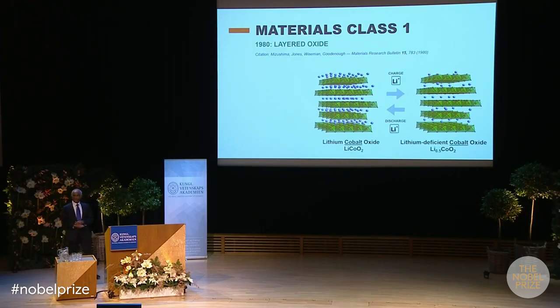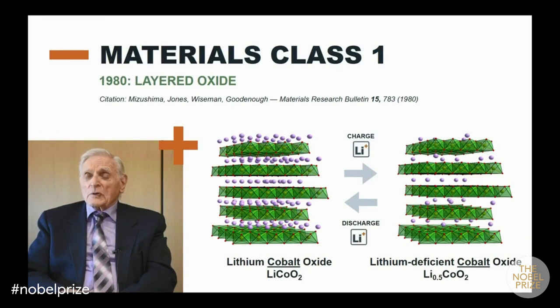The first family of cathodes Professor Goodenough's group developed was a layered oxide. I started with lithium cobalt oxide because it was a layered compound with ordering of the lithium and cobalt in alternate layers. And I investigated how much lithium I could take out of the lithium cobalt oxide before it changed its structure. And I found I could take out over half of the lithium from the lithium cobalt oxide without changing its structure, and I could therefore have a reversible lithium insertion extraction oxide as against lithium insertion extraction sulfide to give me higher voltages.